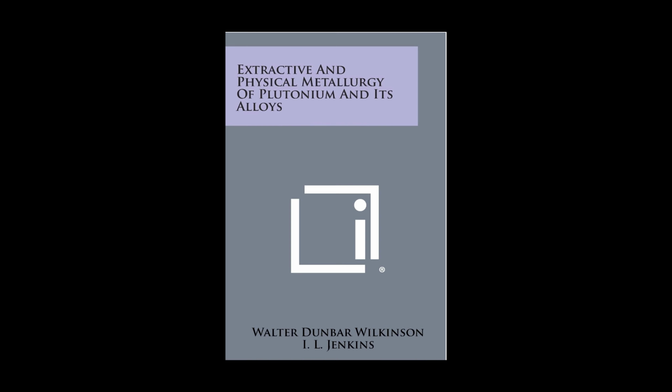And how did they contain the reaction? They used these sealed steel vessels, which they actually called bombs. These bombs were lined with a refractory material, usually magnesium oxide, magnesia, to stop the molten plutonium reacting with the steel walls at the high temperatures involved. A bomb lined with magnesia sounds intense, like trying to contain a mini volcano or something. It kind of was. Figures 1 and 2 in that section show drawings of these bombs and the different liners they used for different amounts of material.